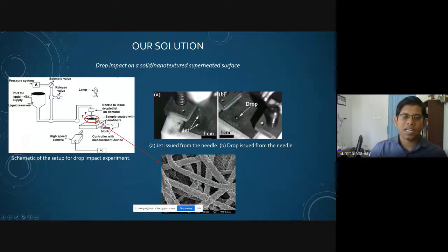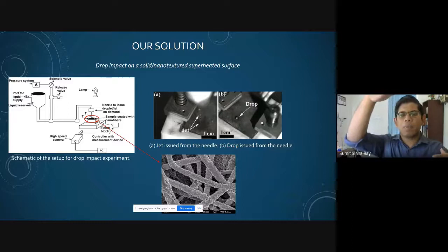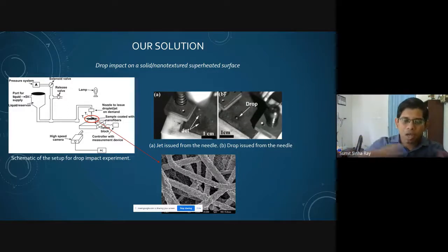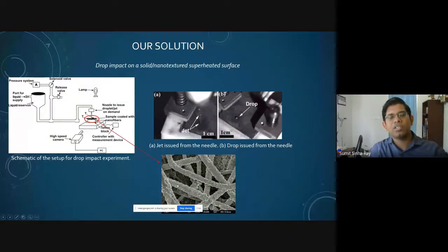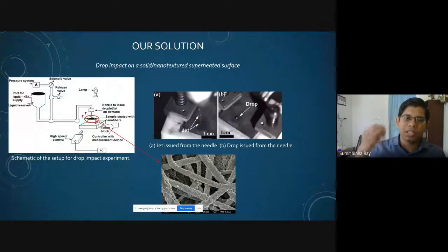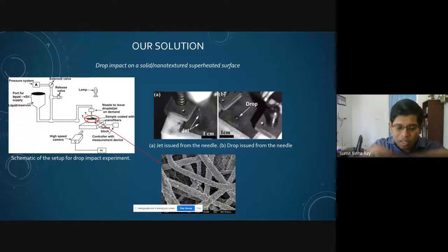Okay, so the idea was that you have this GPU, you place a copper plate onto the hot spot, where the copper plate would be textured like this. These are what we call metal plated electrospun polymer nanofiber. Earlier in one of our studies, we had shown that these electrospun polymer nanofibers can reverse the Leidenfrost effect by wicking the droplet inside the surface when the droplet comes with a certain velocity and hits the surface. As it hits the surface, it goes inside, wicks in, and cannot come out. And once it tries to come out, it chops the bubbles as they try to come out.